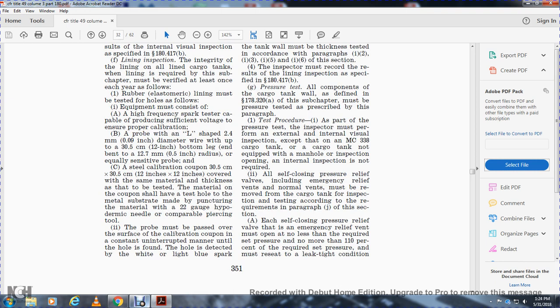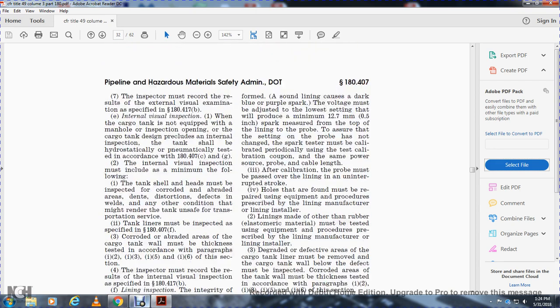The probe must be passed over the surface of the calibration coupon in a constant, uninterrupted manner until the hole is found. The hole is detected with a white and light blue spark. Sound lining produces a darker blue or purple spark. The voltage must be adjusted to the lowest setting that will produce a half-inch spark, measured from the top of the lining to the probe. To ensure that the setting of the probe has not changed, the spark tester must be calibrated periodically using the calibration coupon, with the same power source and probe cable length.